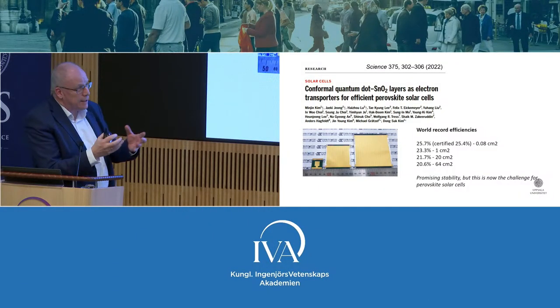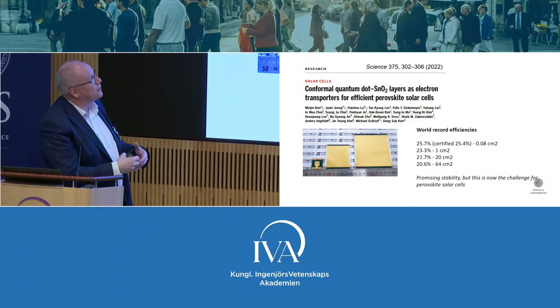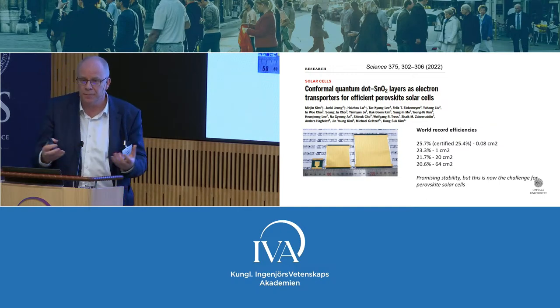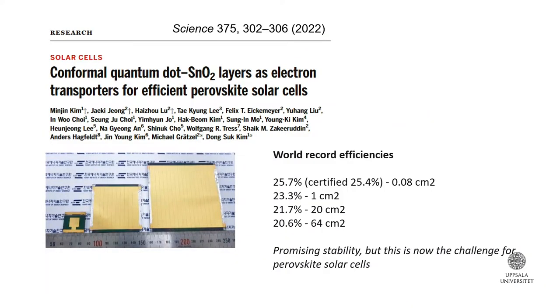You can also work on the contacts, and Tom mentioned the hole transporter. This is a quite recent work we did where we worked on the electron contact instead and started to use quantum-sized tin oxide, just like the Nobel Prize last year with the quantum dots. So these are quantum dots of tin oxide to accept electrons, and then you can tune the energy levels to optimize so you avoid any kind of energy level drops internally. So here we had, I think, quite a world record efficiency. This goes fast. It's probably not a world record anymore, but 23% for a square centimeter, and then scale it up.